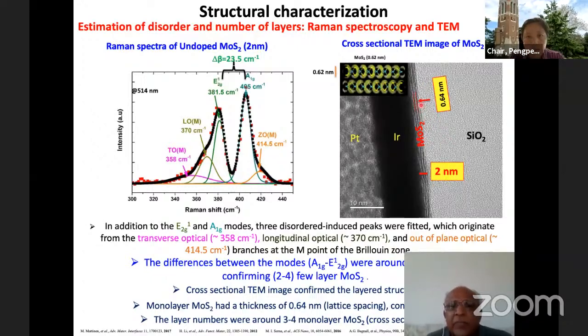Please note that at the interface between the silica substrate and the very first layer of molybdenum disulfide, the film is not continuous. This is discontinuous. As more layers grow, they become continuous. This is a very interesting question, which as a material scientist I find very fascinating, and it tells us how nucleation and growth might be taking place in such 2D films.